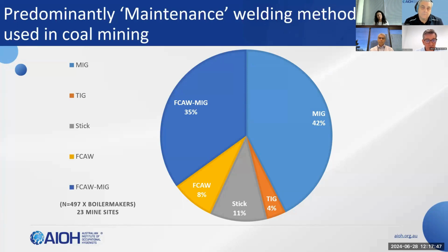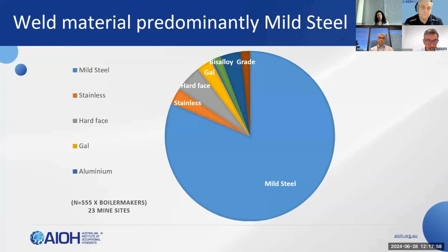There's limited application of other weld methods, including TIG, and particularly stick, which is used typically for short durations and for minor jobs only. The majority of material being welded is mild steel with some hard facing and Bisalloy. Welding of aluminium, stainless steel and galv is relatively rare in this industry. Another important factor to consider is the location where the welding is performed. Most of the maintenance welding is performed in situ, out in the field where the equipment is located, and these are typically in outdoor environments. Welding inside workshop environments is relatively rare and to a much lesser extent than outdoors in natural ventilation.